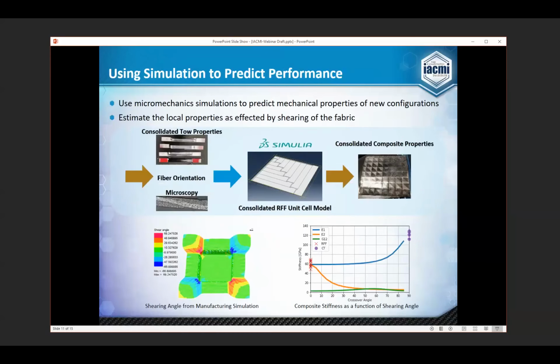And then the next step is, okay, we have this model. We know that as we go through forming, we're going to have different shearing angles, different orientation states. How is that going to affect our mechanical properties? So that's where we can use a micromechanical model to develop the unit cell that describes how the RFF is going to behave, and use that to predict our consolidated properties as they are locally to each point in our performance model. So, in the bottom right, I'm showing that as you shear the RFF fabric, you're going to have different mechanical properties in different directions based on that shearing angle.